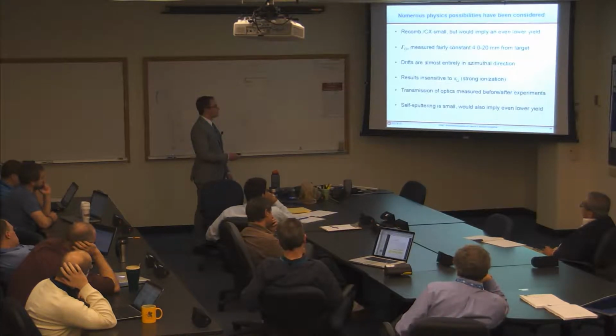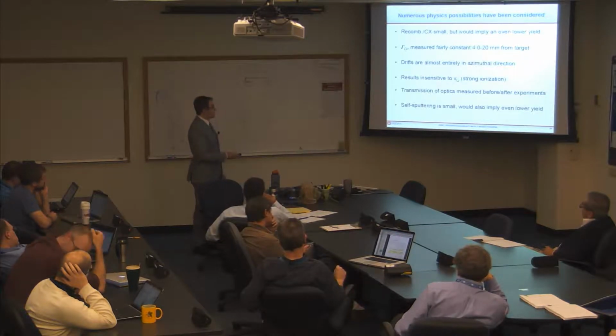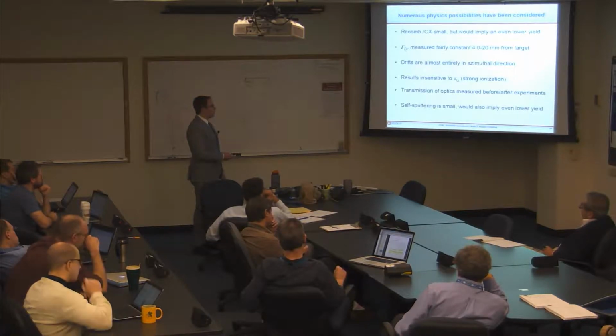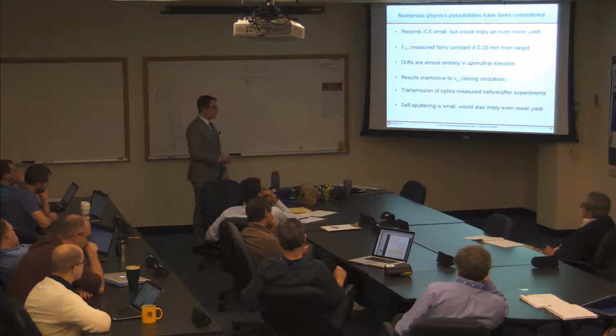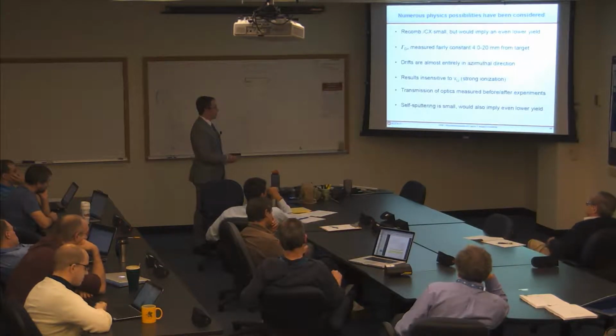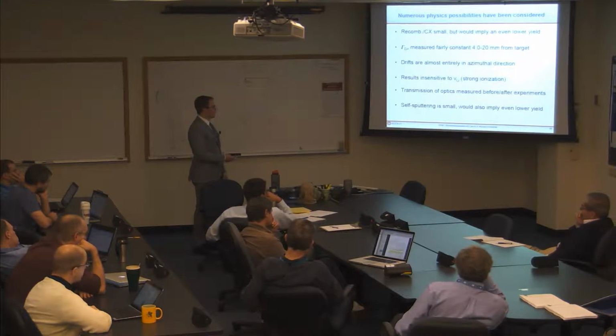We did a scan in Thomson scattering measurements. And the ion current that you measured to the target also didn't really drop too much with the lithium on it. We don't expect drifts to be a factor because electric fields are all radial and magnetic field is nominally axial. So the drifts are all azimuthal, which is an axis of symmetry. The results, as I mentioned before, we talked about this already. The results were insensitive to erosion velocity.